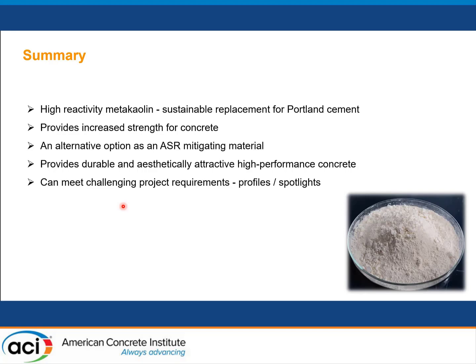Thanks so much, Frank — lots of great examples of large-scale projects and great lab data. A question from Mohamed Jabirazita: What was the goal of air entrainment in MetaKaolin-containing concrete? Yes, most North American outside projects require air entrainment for freeze-thaw resistance. One of the key points is that even though we have 6–7% air content in the concrete, by using MetaKaolin, the permeability is still very, very low. We still need air entrainment to provide freeze-thaw resistance — it addresses two different durability issues: one is ASR mitigation, and the other is freeze-thaw resistance.